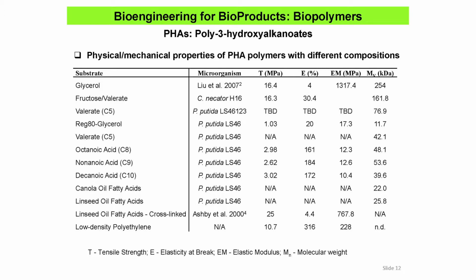There we go. But they're not very elastic, whereas polyethylene is very elastic. PHB, which is 100% C4, is very brittle. It doesn't stretch at all. If we add a little bit of valerate to it, it becomes a little bit more elastic, but not as much as this. And the molecular weight decreases as the subunit chain length increases.